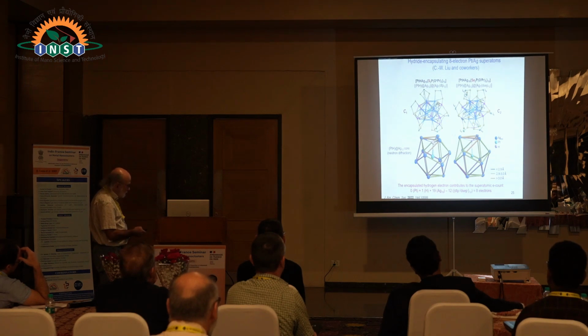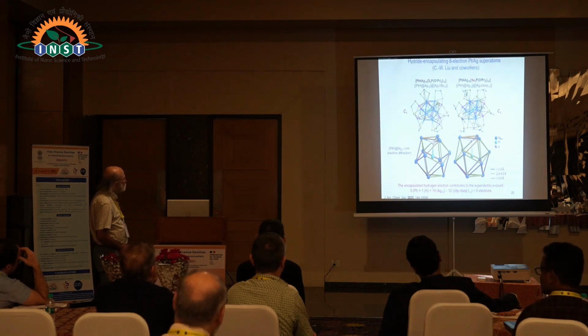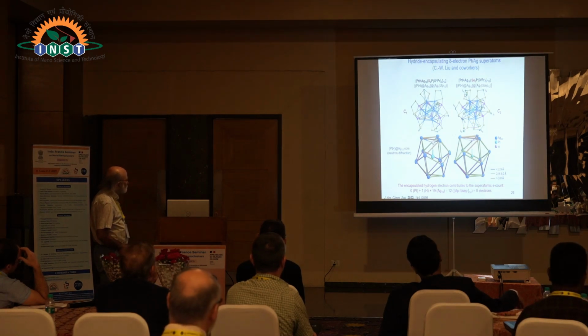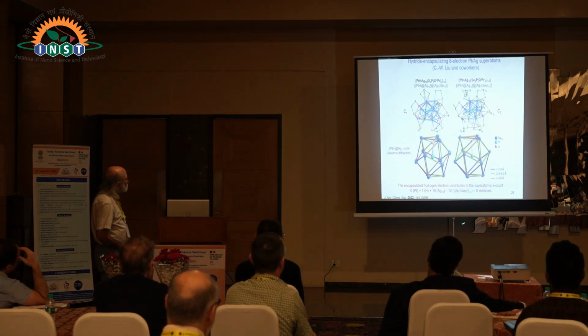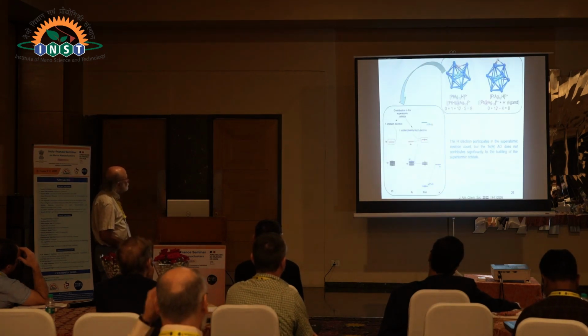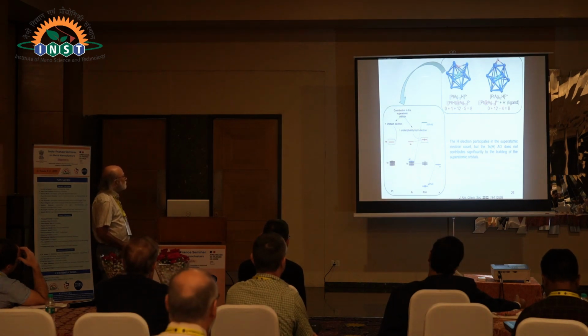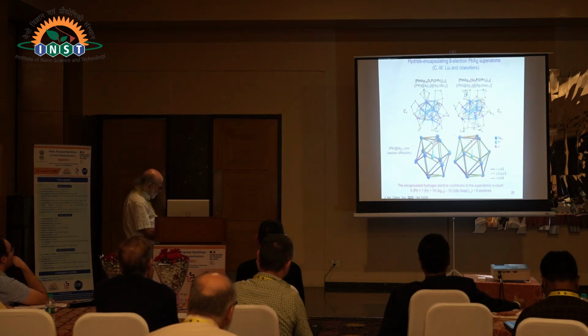If we want to get the 8 electron count, and I will tell you this is what we have to do, we have to count the electron coming from the hydrogen atom in the sum to get 8 electrons, because platinum is a 0 electron donor, hydrogen 1, 12 silver atoms, -12 minus the formal charge of the ligand equal 8. To understand this, let's look at these two. These are optimized structures, DFT optimized structures. There is no outer shell, but if we consider some outer shell, we get the same results. So let's look at the core. Let's look at this one first.